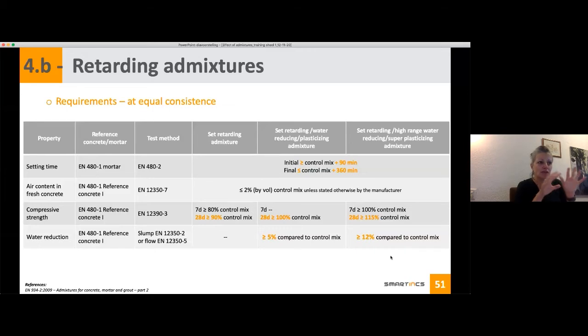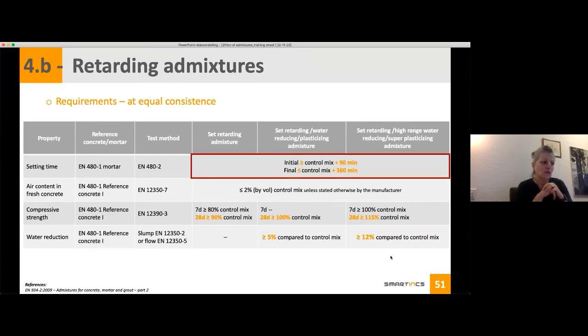So what are the requirements? Here the requirements are at equal consistency. And you see that the first requirement is dealing with the setting time, because we are retarding the setting time. So no matter if you are using a set retarding admixture, or a set retarding admixture plus plasticizing effect or super plasticizing effect, the delay of the initial setting should be higher than your control plus 90 minutes, and your final set should be less than the control mix plus 360 minutes. So this is for all categories.